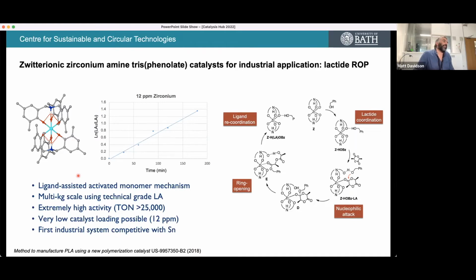conditions. And to cut a long story short, what we have is these zwitterionic zirconium phenoxides, which, in contrast to the previous zirconium system I showed, don't have a labile alkoxide group. They're pretty stable and robust species. They're actually air stable. But it turns out that they're very good catalysts in a similar way to tin carboxylates. They're very good catalysts for the ring opening polymerization of lactide under industrial conditions.